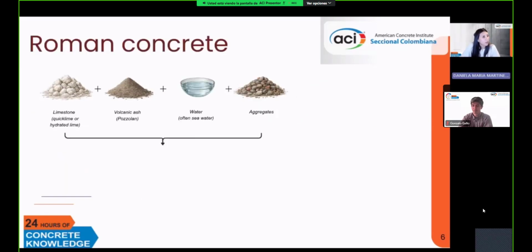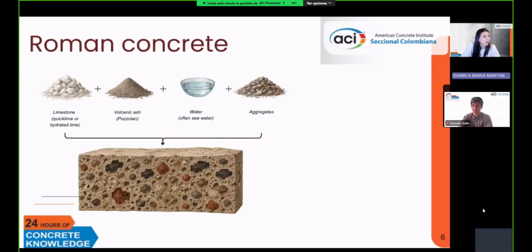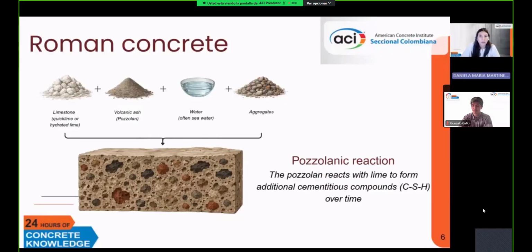So the key chemistry in Roman concrete was activated by the pozzolanic reaction. Now, this pozzolanic reaction means that the volcanic ash would react with lime to form additional cementitious compounds such as CSH over time. So this is the first difference with our modern concretes, where CSH is also the binding mechanism, but it forms rather quickly and not over time like with Roman concrete.